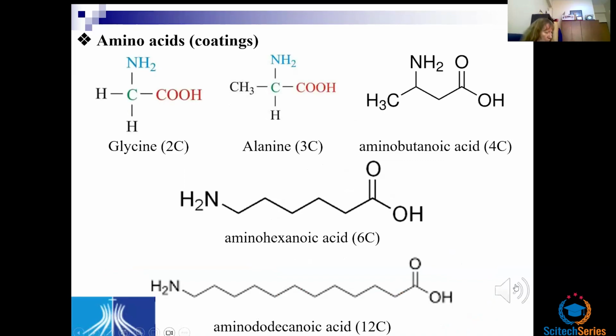This slide shows a collection of amino acids that were used to perform the surface coating. So if you look at the structure in the slide, you can see glycine is the amino acid with only 2 carbons in the structure. Alanine has 3 carbons in the structure. And aminobutanoic acid has 4 carbons in the structure. And in the middle of this slide, the aminohexanoic acid has 6 carbons in the structure. And finally, the longest carbon chain is found in the aminododecanoic acid, which has 12 carbons in the chain. So this shows you an increasing thickness of the surface coating.